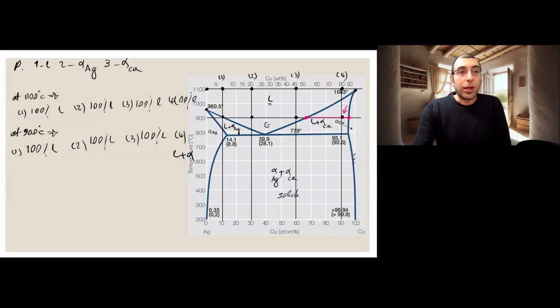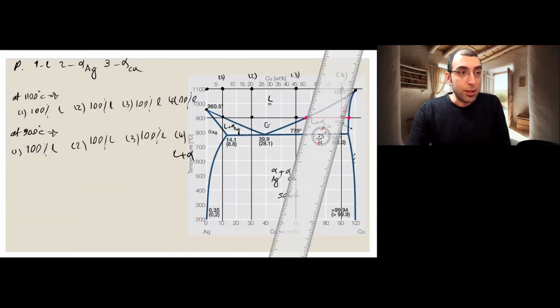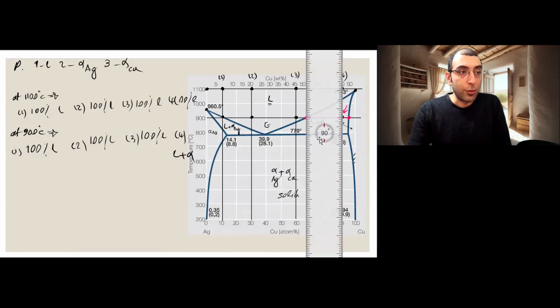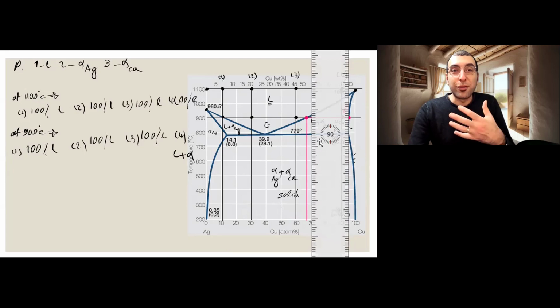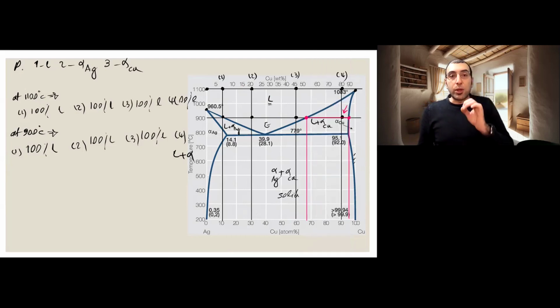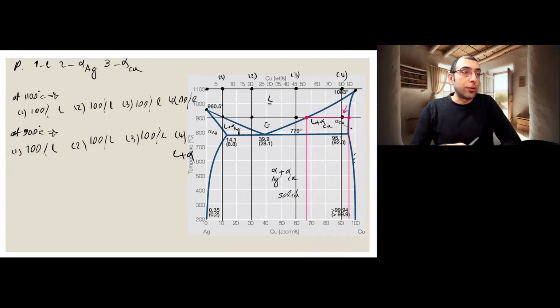When you figured out these cross sections, when you did a horizontal line, you also drop it down. What I mean by dropping it down, from where it crossed the liquidus line, you make a vertical line now, to get the compositions. So the horizontal line is mostly for phase fractions and the vertical is for compositions. Every time you want to do phase fraction and composition, you do a horizontal line, it crosses the borders. When it crosses the borders, you drop it down to go for composition.